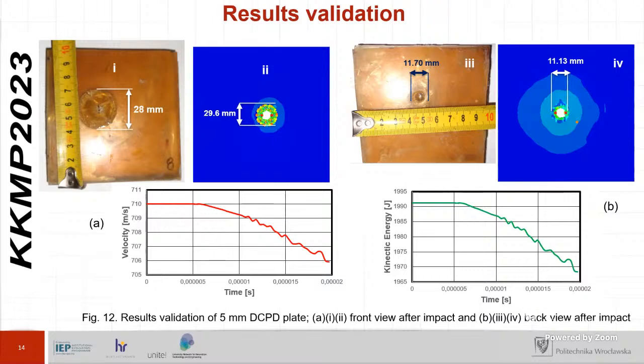For the bullet itself, it is also important to show how the velocity of this bullet drops with time. The flat region here is when the bullet is in the air and has not touched the sample yet. By the time it touches the sample, you can see how the velocity drops until here. When the velocity gets to zero, it means the bullet stops. That's the implication. But you can see that it's not up to zero here. It's just from 710 down to somewhere around 706. So it means the bullet was still going. But we don't need that information. The information we need is that there was a complete penetration, and that's why this velocity drop does not get to zero.